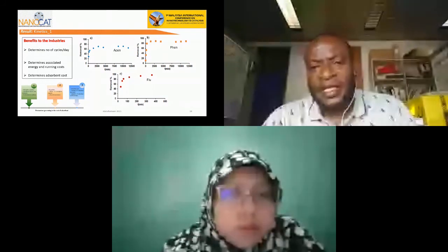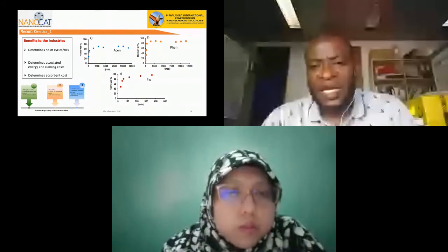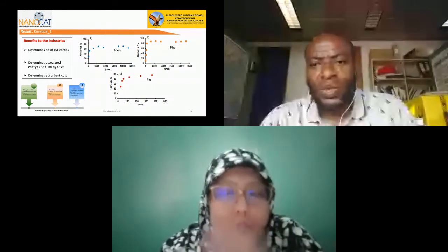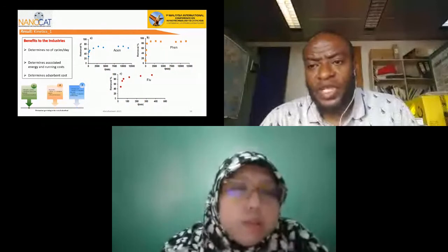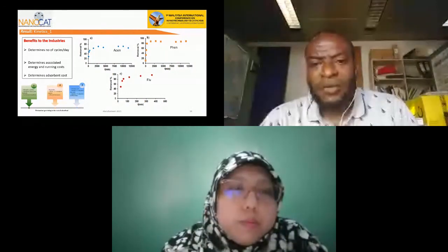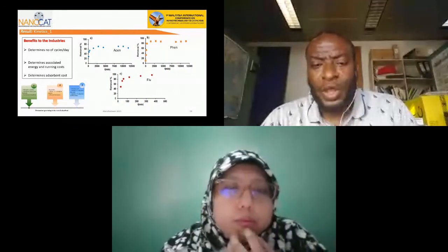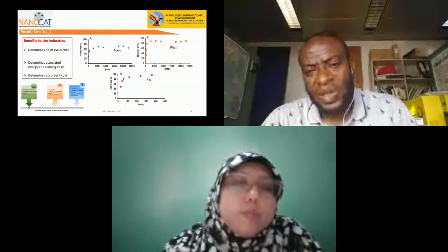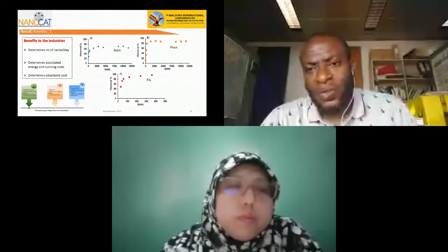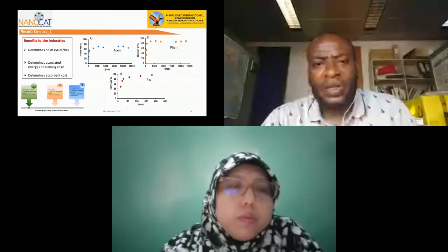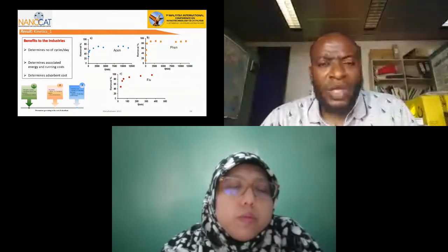So in this experiment, we varied the time from 5 minutes to 12,500 minutes. And fluoranthene was able to reach equilibrium around 6 hours, followed by phenanthrene, which reached equilibrium around 24 hours, and acenaphthylene, which reached equilibrium around 120 hours.